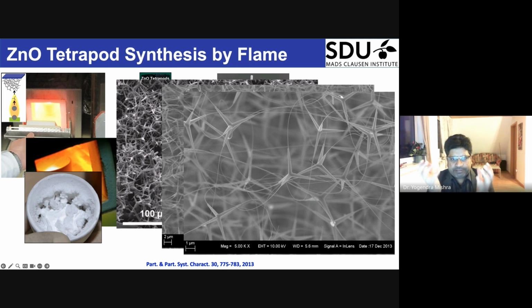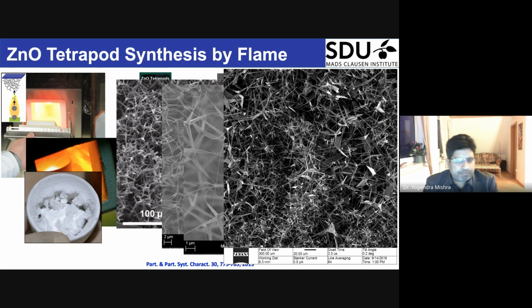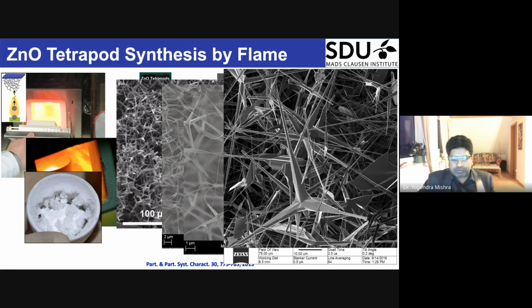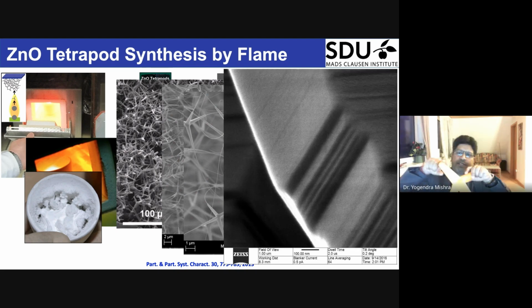Usually these tetrapods come as a loose powder, and you might assume that each of these arms is quite a huge, cylindrical, uniform cylinder. But this is not the case. If we go from bottom to top, then we can see that we have a lot of screw-like structures, edge-like structures, steps. Basically, this structural arrangement of the surface adds more surface area. In this way, these tetrapods are very, very good. There are no other materials in these tetrapods. They are completely pure, but at the same time there are a lot of structural defects in boundaries and structural defects.